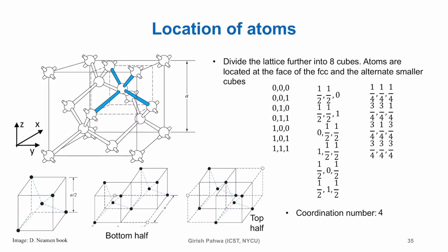By the way, I forgot to talk about the coordination number. So what is the coordination number? The coordination number is going to be 4 here. FCC had 12, but this is not FCC. These are actually 2 FCCs, interpenetrating. So the coordination number here is 4. Why? Very easy to see. What's the smallest distance of this point to other points? This, and this. That's it. All the other points are actually farther. So that's why the coordination number is only 4.